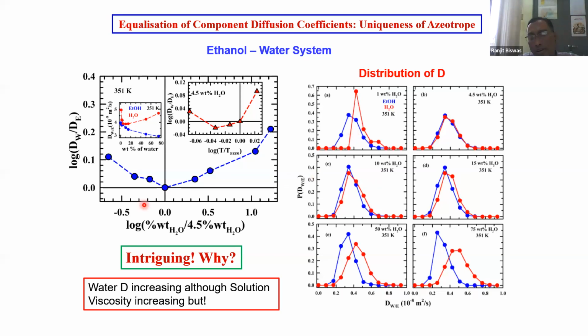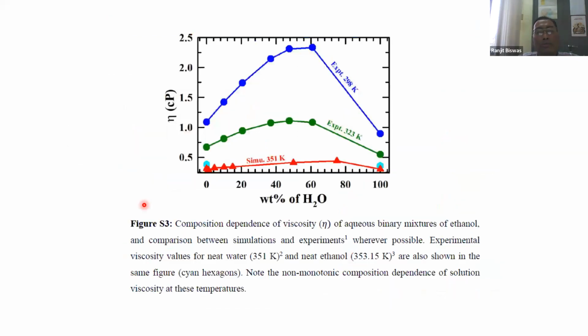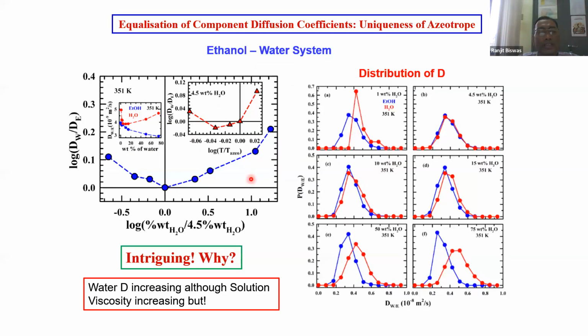And this is intriguing because in the next slide I'll show you that we are in this area of low water content where the viscosity is increasing. But what we are seeing with the diffusion coefficients, you see here that the water diffusion coefficient in this plot is going up. Very interesting. Ethanol is going down, but water is going up. So water is behaving in a very anomalous way.